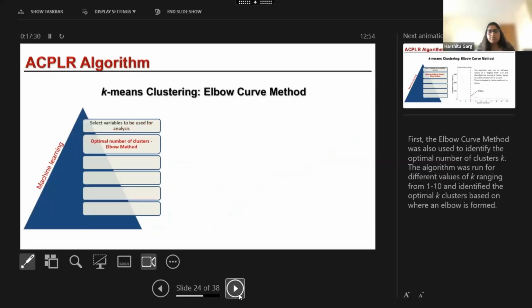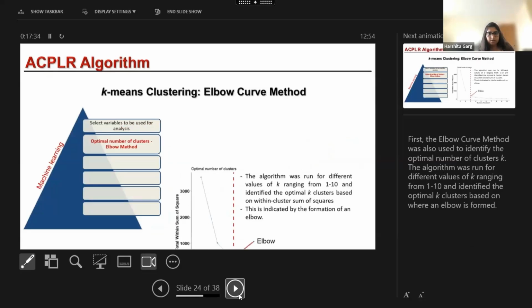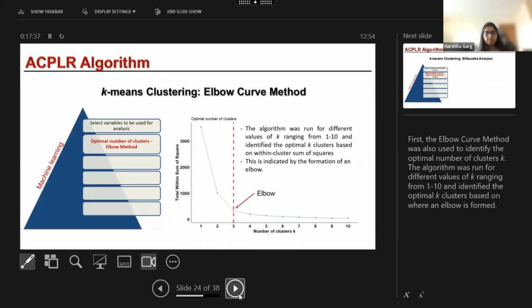In order to find that, we've got the k-means clustering algorithm, which has a first method called the elbow curve method that identifies the optimal number of clusters. So basically the algorithm runs for different values of k from 1 to 10, and based on within-cluster sum of squares, it identifies the value of k clusters. Where there is an elbow formed, as seen here, it shows that this is the optimal number of clusters, so there are 3 clusters.